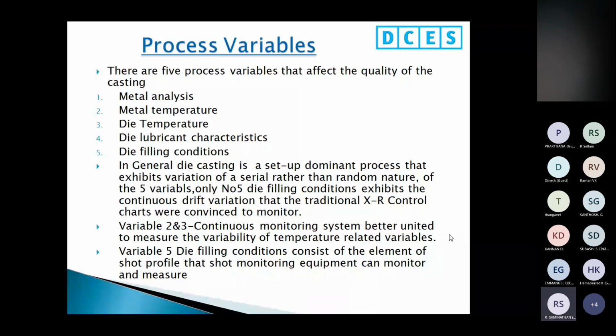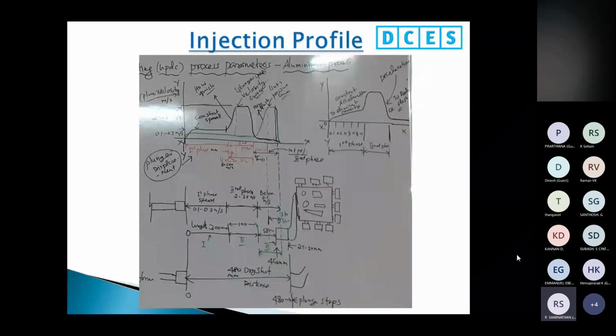This is one type of injection profile, hand drawn by myself during an internal discussion in our office. Here you can see my cursor. This is the constant speed curve. This is a constant acceleration curve. If you use the curve on the right side, a constant acceleration curve, you can evacuate all the air in the shot sleeve, so you can reduce the porosity in the casting. That's why I'm showing it here. This is only one important point in the injection profile. Others are normal: the second phase and intensification take 4 points on.